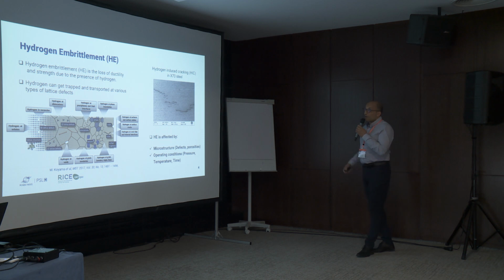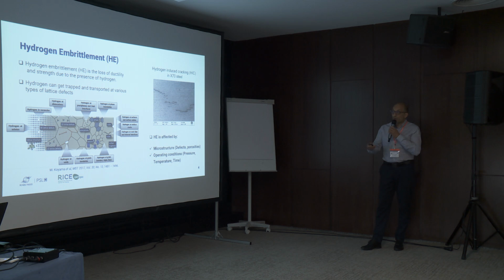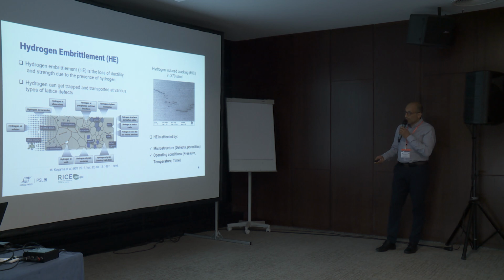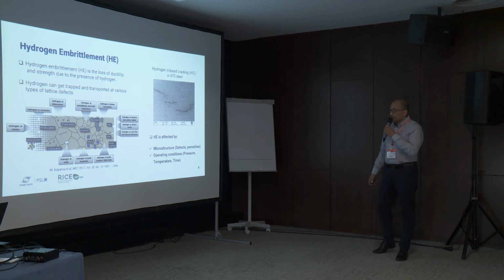Hydrogen embrittlement is the loss of ductility and strength due to the presence of hydrogen. The key point is hydrogen trapping and transportation of various types, as we see in this specific session. It is affected by microstructure, defects and porosity, and operating conditions. With gas we have pressure, temperature and time. Here you can see an example of hydrogen-induced cracking of a line pipe steel.